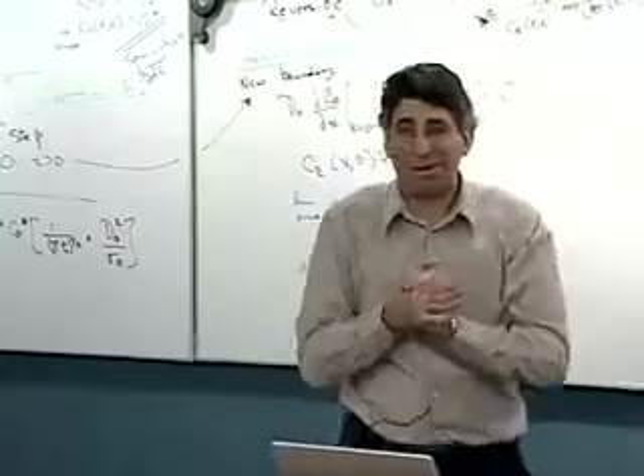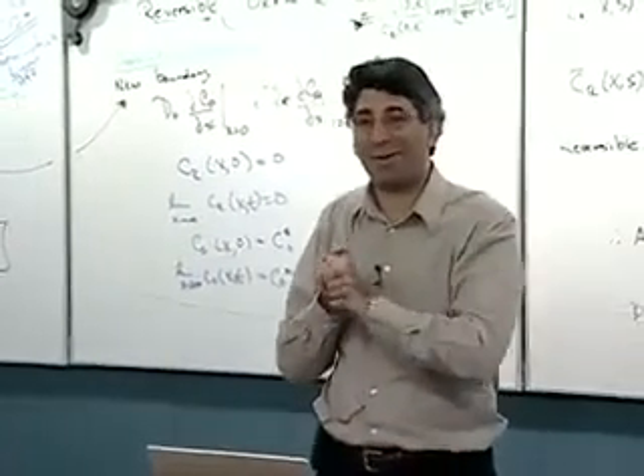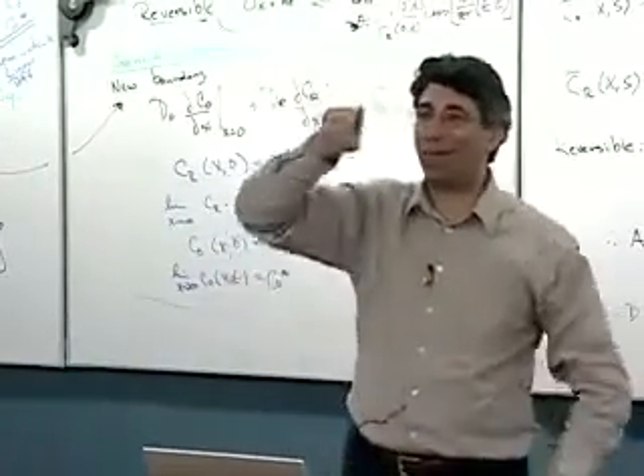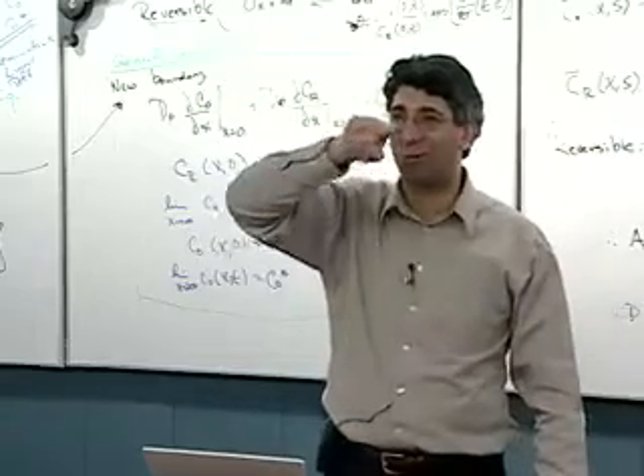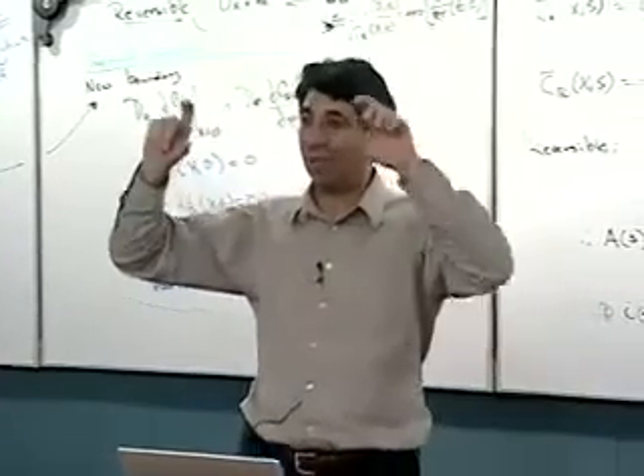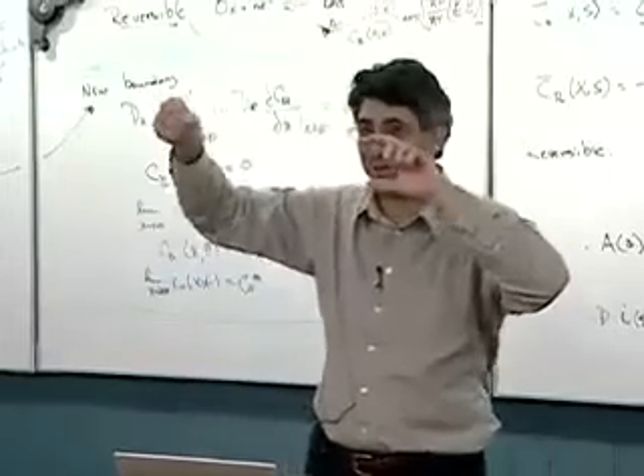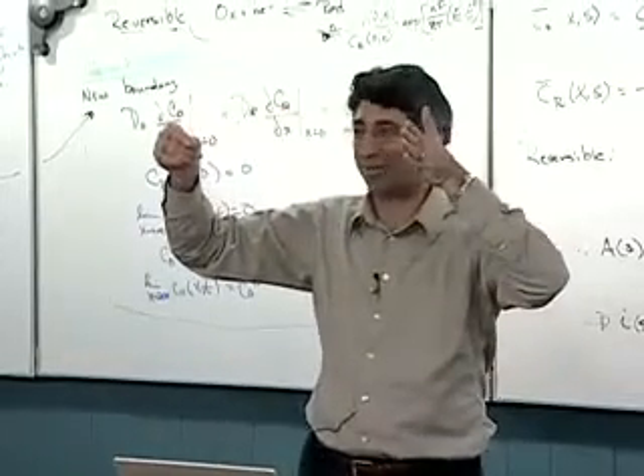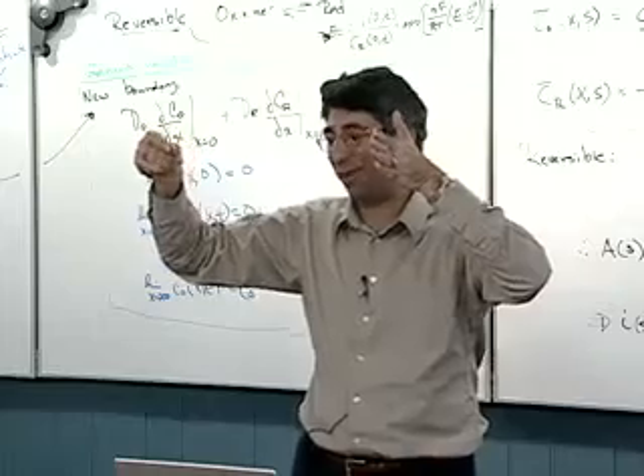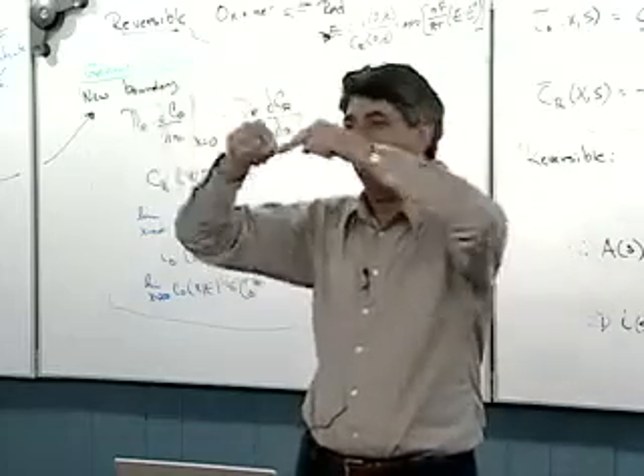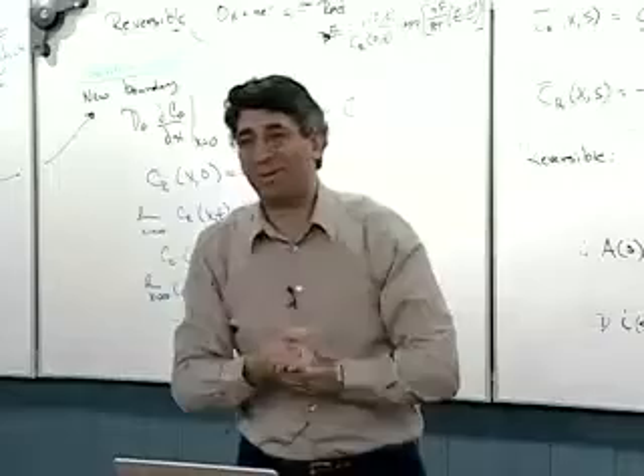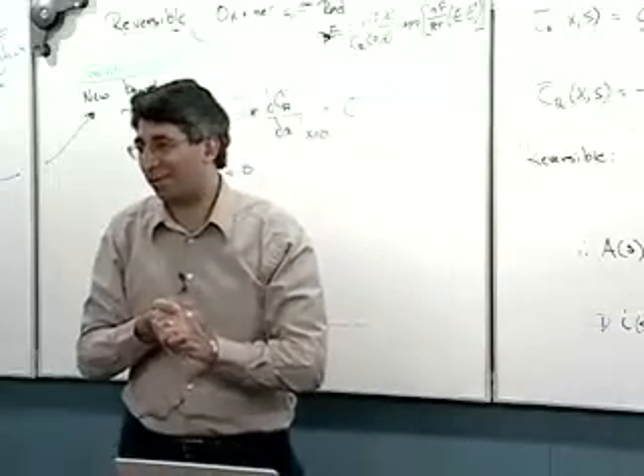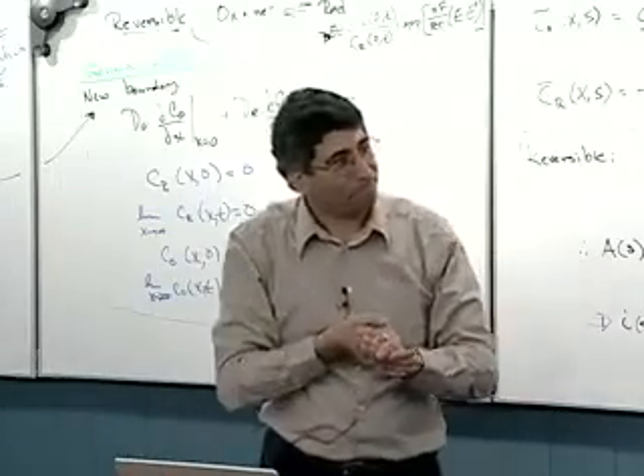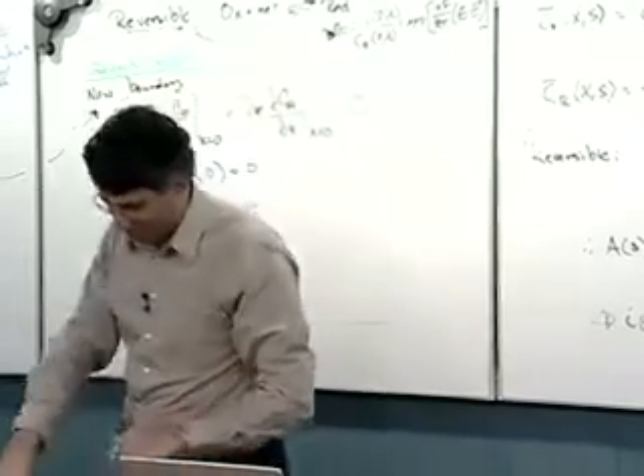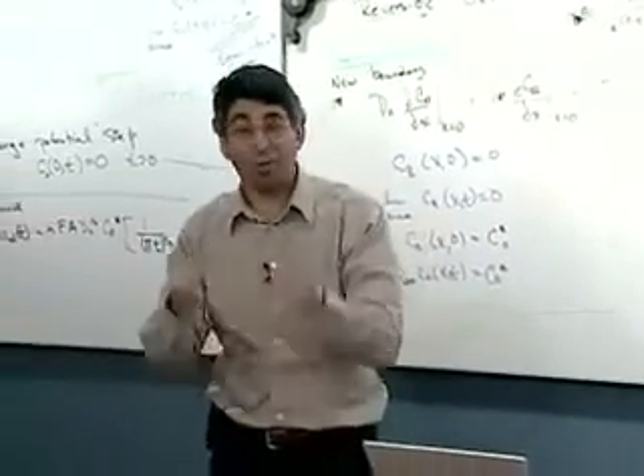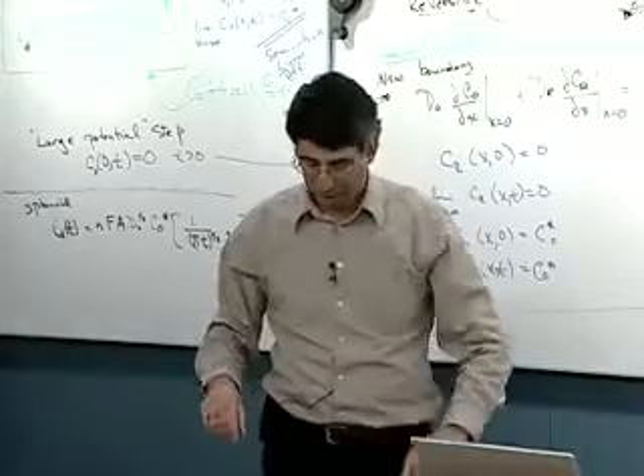And if you want to spend a lot of money and take apart your rear view mirror that does this, you'll see that they've made electrical contacts all the way around the perimeter of the field. They don't have an electrode like you would make, where you have one wire coming off one end and then a big potential drop as a result across the mirror or the electrode. But they're connecting about 100 points around the mirror in order to try and even out that electric field. So that is another issue to keep in mind. So small electrode, but there will be edge effects. Even having said that,